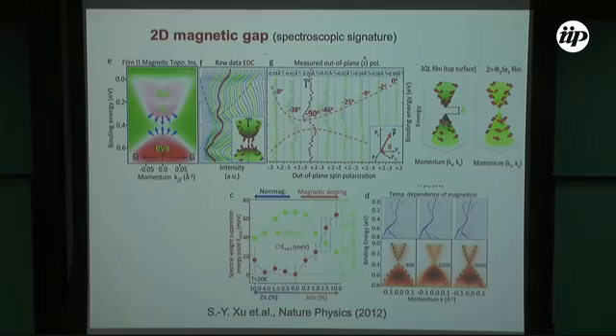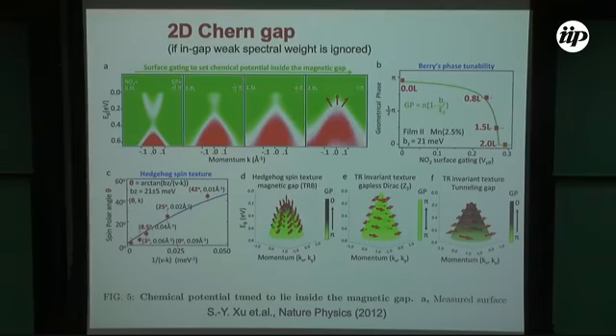For example, if you place your Fermi level here, there's a net moment on the Fermi surface, on the surface Fermi surface, right? That is not the case in the topological insulator that is undoped. And the way the spin texture is disrupted in the magnetically doped case has a characteristic signature. And not only that, it also has a temperature dependence. So that is telling us that it's related to an interaction that is involved.